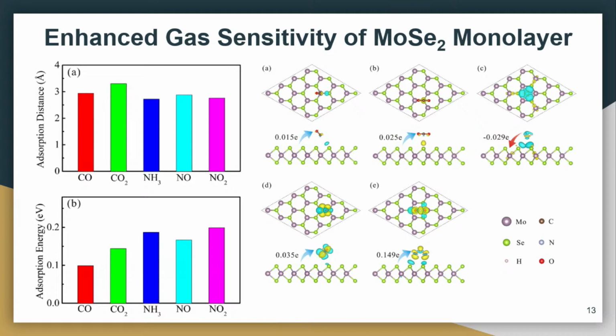But here you can see, even though your NO2 has a higher charge transfer from your material to your gas molecule, NH3 and NO2 have the same adsorption energy. But what we are expecting is that your NH3 also has a higher charge transfer. But here you can see the charge transfer is very, very less. It's minus 0.029 electron, but here it's like 0.149 electron. But the adsorption is so similar. But then they conclude that here the charge is transferred from the gas molecule to the substrate, but here it's from your substrate to the molecule. So they believe that molybdenum selenide is a wonderful candidate for NH3 sensors without applying a biasing voltage.